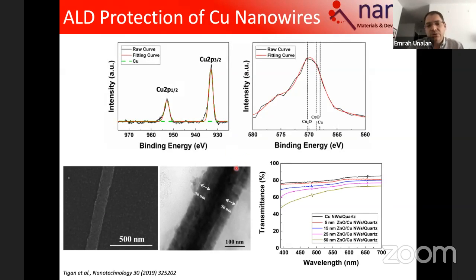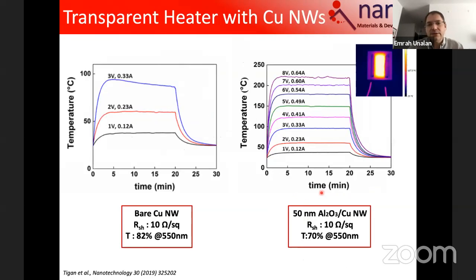In this case, we are using atomic layer deposition to put thin layers of oxides. We tried aluminum oxide and zinc oxide. As you see here, the core is the copper, and the sides are the zinc oxide. And it's a ceramic material for sure. It increases scattering because the radii increases, so the transmittance drops a little, but certainly it protects the nanowires.